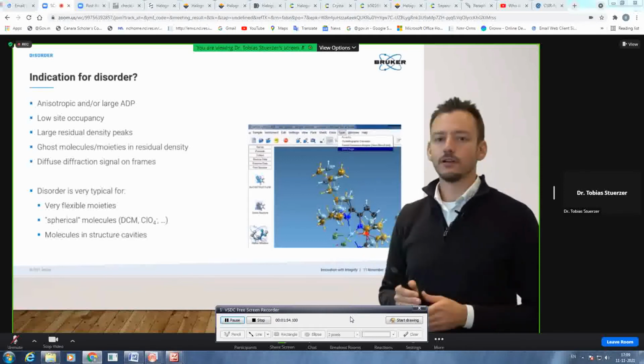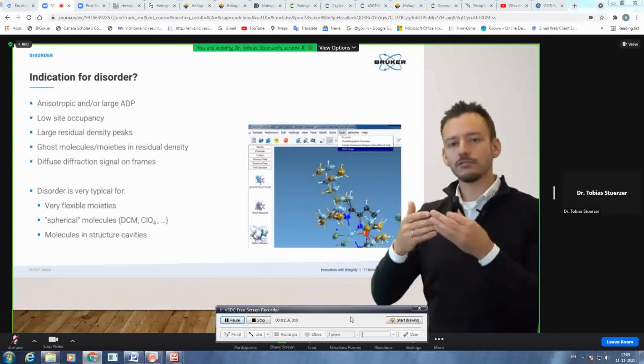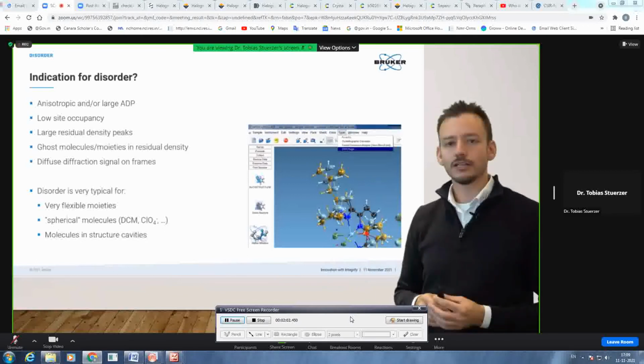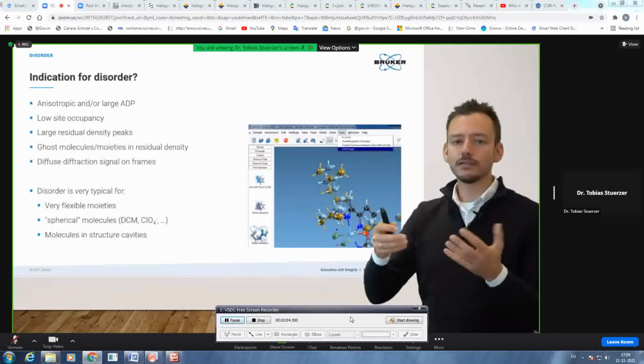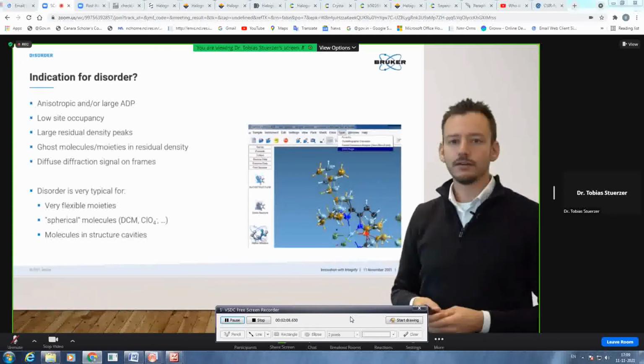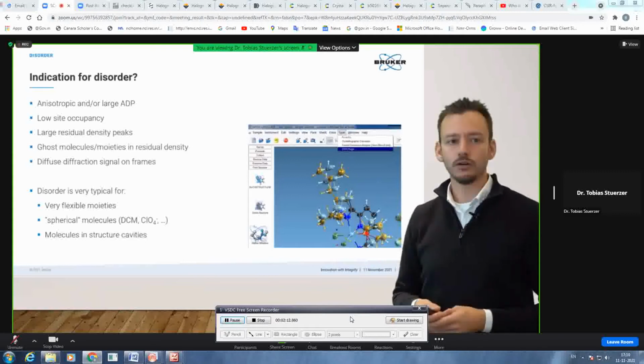The more you deviate from the strict periodicity, the more parts you see from the structure factor function. That means the broader, the more smeared, the more streaks you get in your diffraction pattern, the more sure you can be that there is a lot of disorder going on.